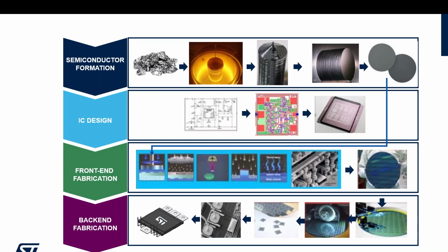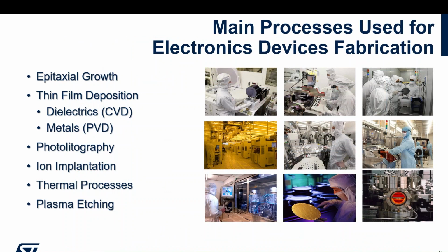Then you make the design of your device, so you understand what the structure should be, and then using a variety of processes, you go to the front end to actually implement on the substrate this structure that you have conceived. And finally you go to the back end in order to connect to the external world. So in a nutshell, the processes that we are familiar with in the production of a silicon device are: growing epitaxy wherever needed, as in power; thin film deposition by a variety of means, where thin film means dielectrics and metals; litho, a lot of litho, in order to define the features that you want to achieve on the surface; ion implantation for precise positioning of the dopant and controlling of p-type and n-type doped layers; thermal processes for activating the dopant; and plasma etching. All in a clean room environment, of course.